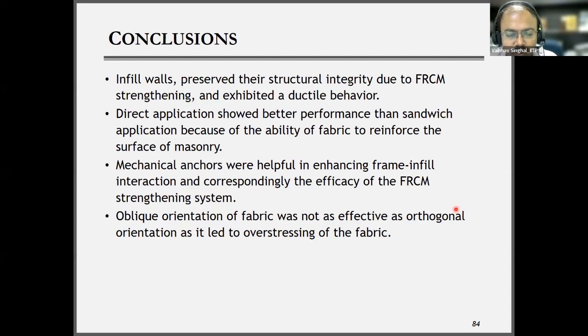The oblique orientation was effective in increasing the strength, but it was not as effective compared to the orthogonal orientation because it led to overstressing of the fabric, because of which we have seen that there can be large out of plane deformations.